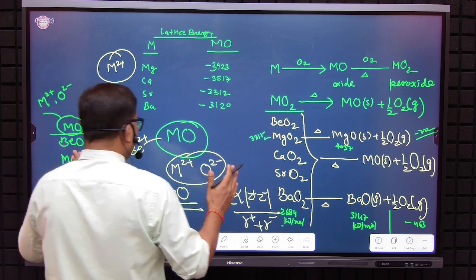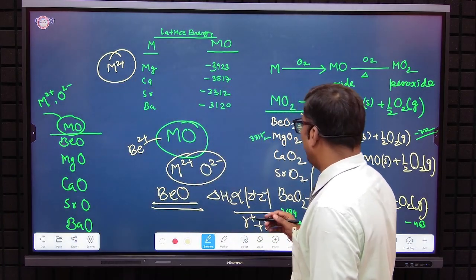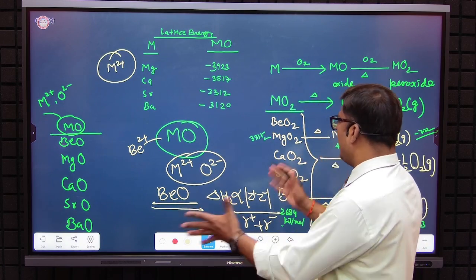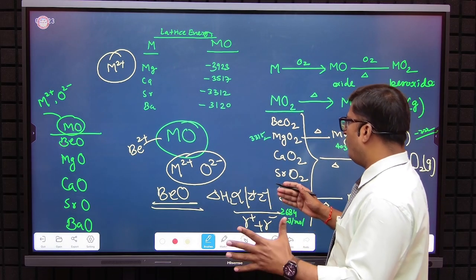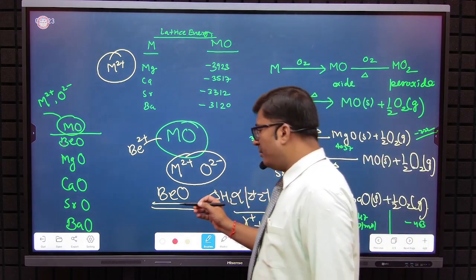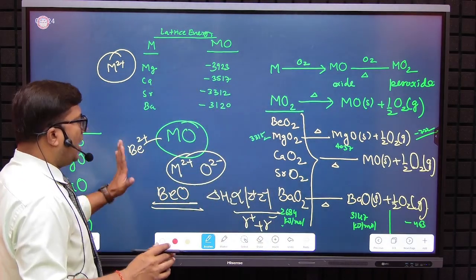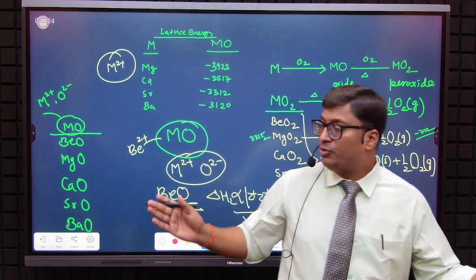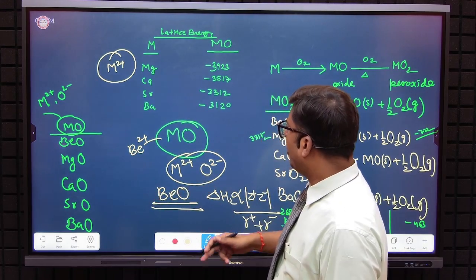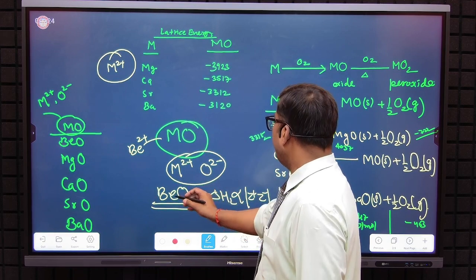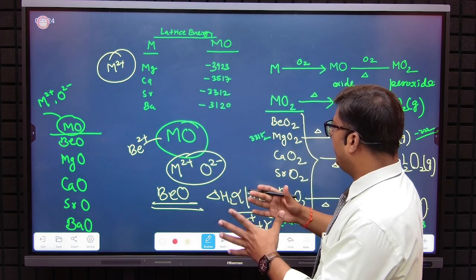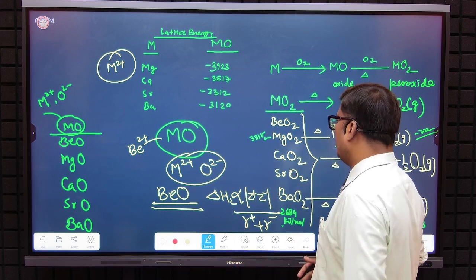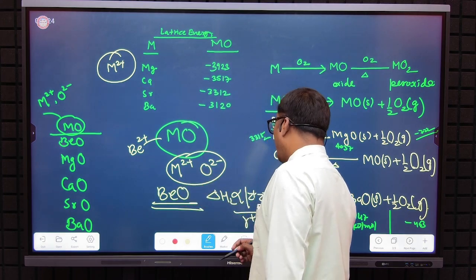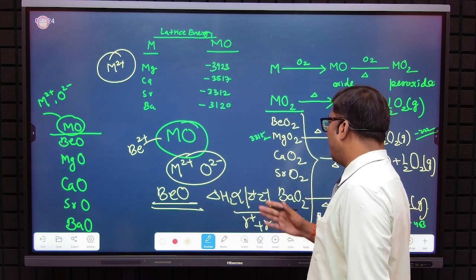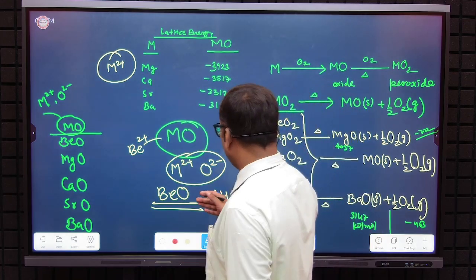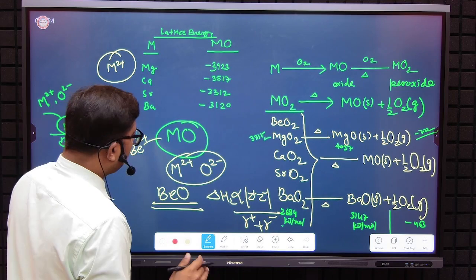So they are more stable, and in general, because of the high lattice energy, it should be most stable. But here beryllium actually exists as a hydrated ion. This beryllium 2+ is a small, highly charged cation, so it polarizes the electronic cloud of the Be-O bond, and the stability decreases because of the covalent character. So these compounds are not very stable at ambient temperature; rather, they are decomposed or highly reactive.